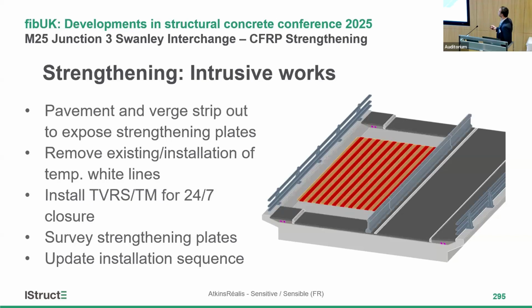Then the second step was to remove the surfacing, where the pavement and the verge strip were removed to expose the strengthening plates. Then white lines were installed to identify where the steel strengthening was and wasn't, as we saw in one of the earlier pictures. Then we installed the temporary vehicle road system. Then a survey of strengthening plates was carried out for records to see the amount of debonding that we have.